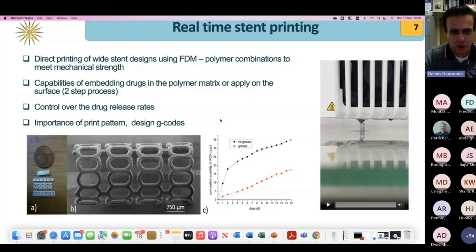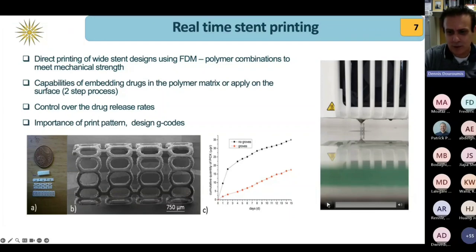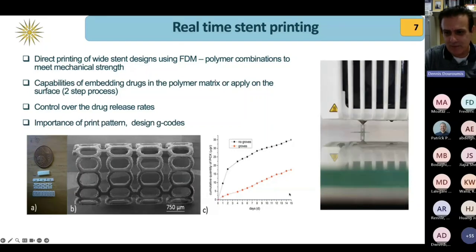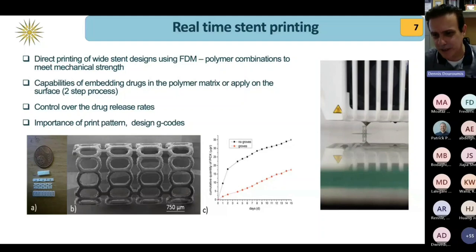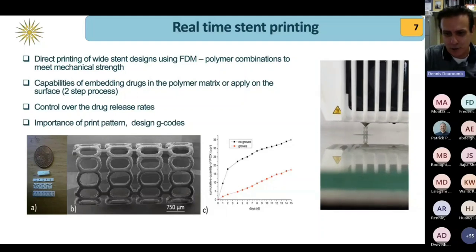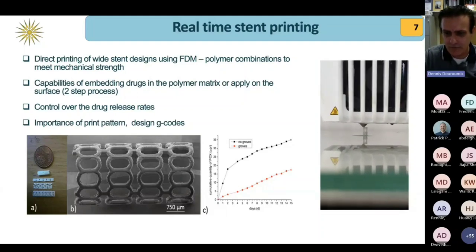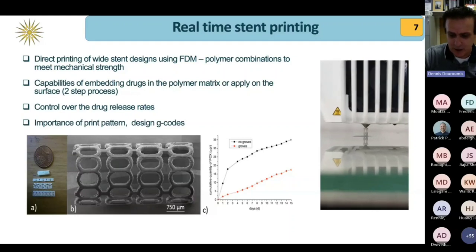So you can see some of these different designs on the left where we could print, but of course that doesn't mean that all of them are successful. You can see in the middle image the different release profile depending on the deposition of the API on the surface. We could play a lot with that. This is a video clip which shows how we can print a stent by using FDM. The printing time for a miniature device like that was about 2 minutes, which was quite good. So that was the first generation of stents that we started developing.